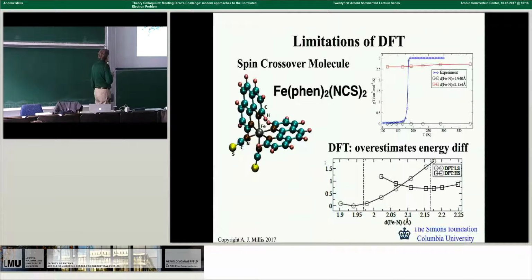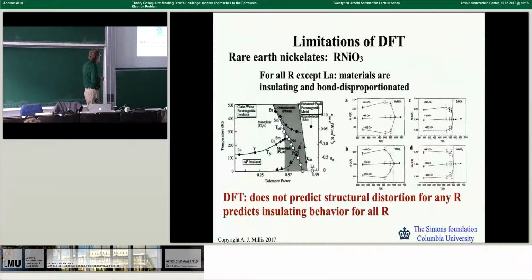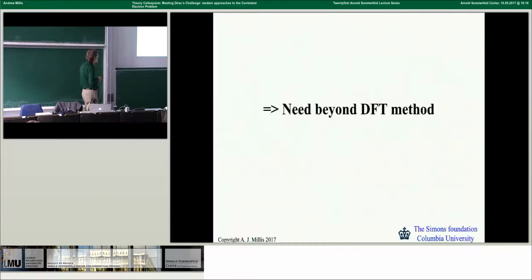You can ask what are the high and low spin states. You can get them in density functional theory, and density functional theory grossly overestimates the energy difference. This is an energy in eV scales. You have a low spin state, you have a high spin state. They differ by 0.6 eV. That's way too big to get a transition here. Right? Here's another example, these nickelate things. Density functional theory doesn't predict that this structural transition, which I alluded to before, occurs. All right? And it predicts insulating behavior for everybody.